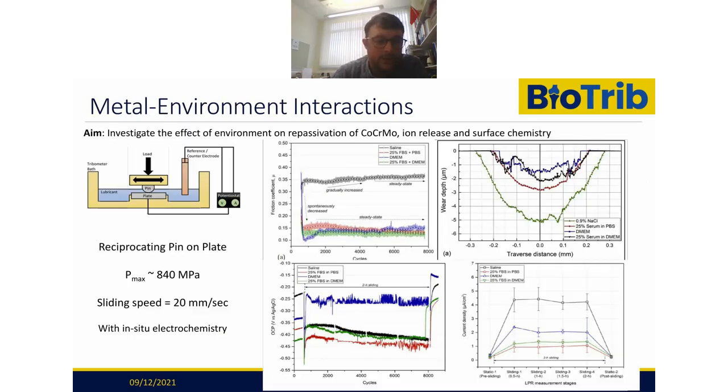Similarly, we've done these under shear, and we can see again the effects of the lubricant on the OCP. So we see this typical depassivation, but the nature of the organic species within these layers affects the electrochemistry, and it also affects the friction. When you have organic species within these lubricants, the friction is usually a lot lower compared to non-organic containing lubricants. And that's nothing new, that's been established for a long time. But what's interesting is that you can have an organic containing lubricant and the rates of corrosion can be very different, and they don't seem to correlate with either the wear or the friction.